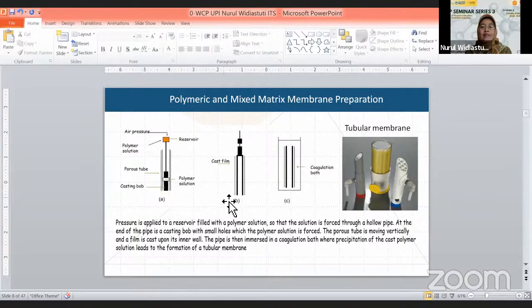So the pipe is then immersed in a coagulation bath where precipitation of the cast polymer solution leads to the formation of tubular membranes, same as the other types of modules.